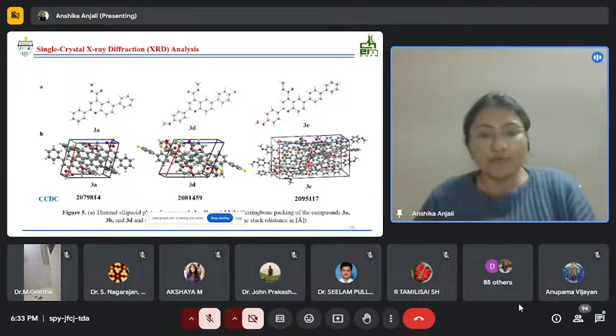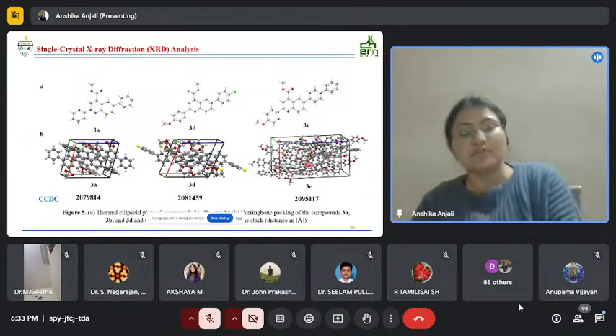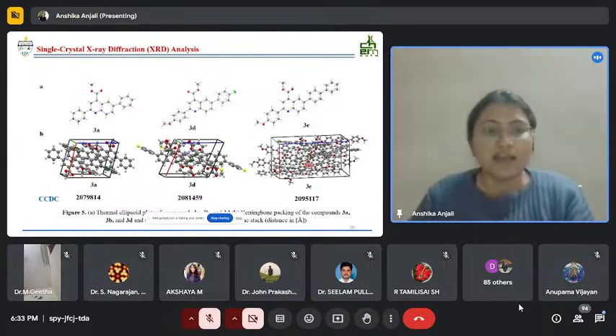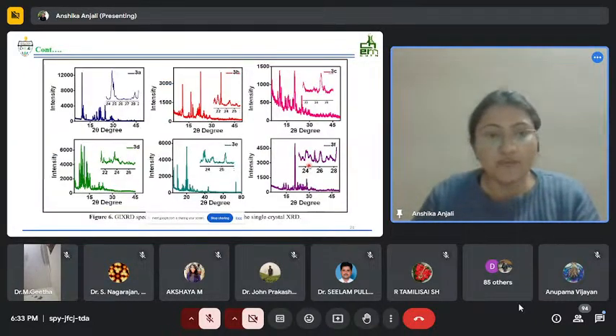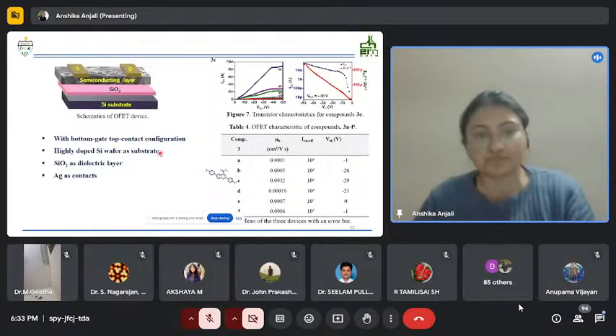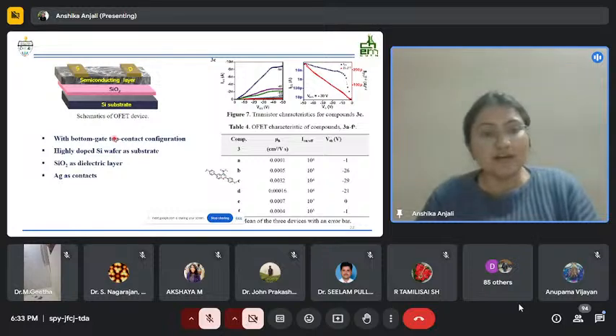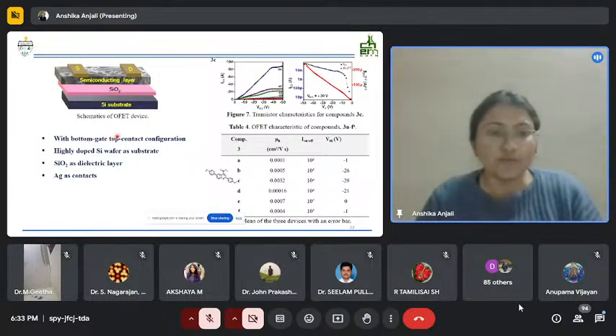So we were able to crystallize most of the compounds, and this is a single crystal XRD analysis of those compounds. We have recorded their GIXRD patterns as well, and the sharp peaks do represent that the films formed were polycrystalline, and they do have some self-assembly in them. So for these compounds, we have fabricated OFET devices.